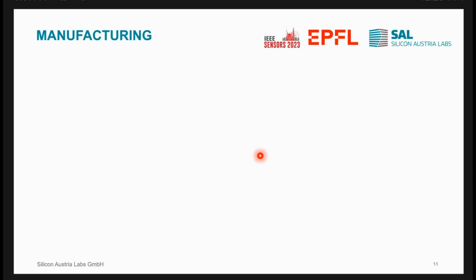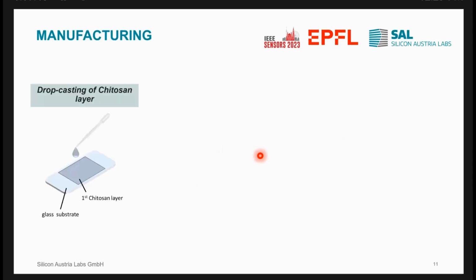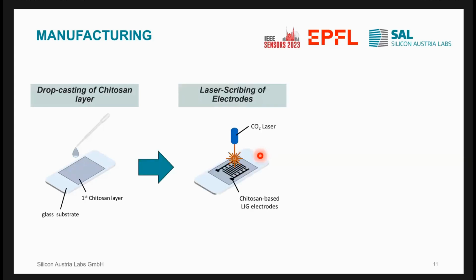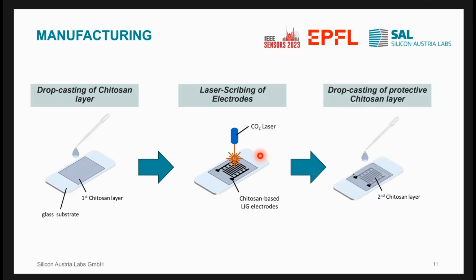So this is the concept, and the sensor design consists of only 3 steps. In the first step, Chitosan is drop cast onto a glass substrate. Afterwards, the electrodes are laser scribed using a commercial CO2 laser. And in the third step, a second protective layer of Chitosan is applied onto the electrodes, as graphene can be quite sensitive or unstable in humid environments.